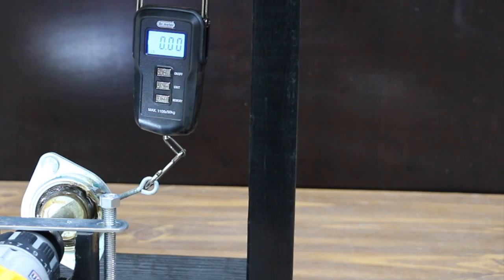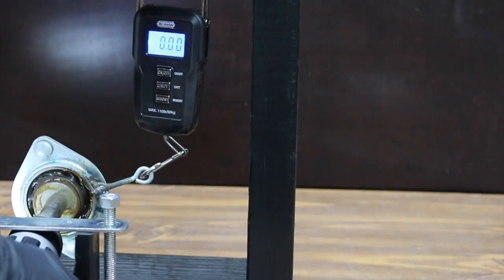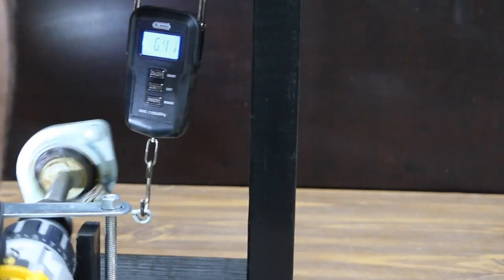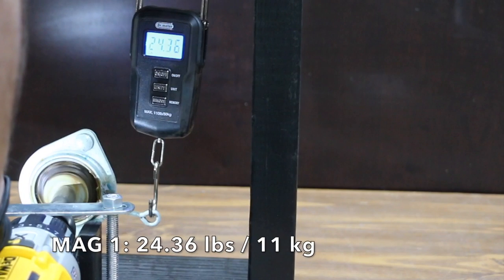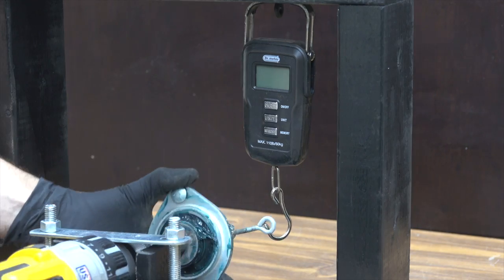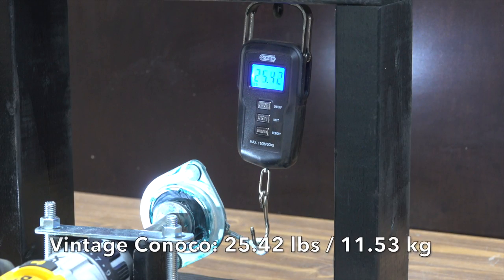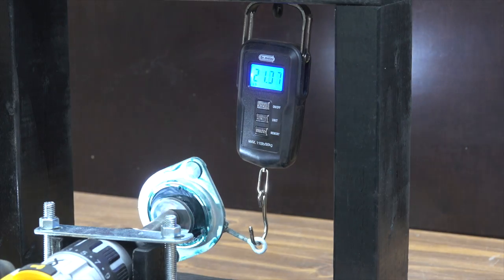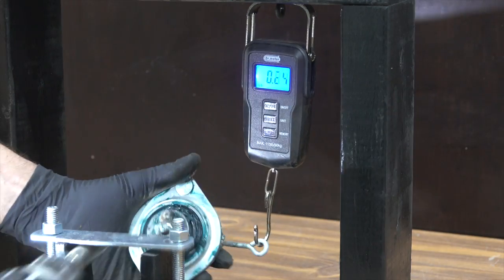It's been right at 24 hours since the bearing was placed in the freezer. Let's first test the Mag 1 grease and we'll measure the resistance to motion in pounds. It took a little over 24.36 pounds to rotate the bearing packed with Mag 1, which is actually sort of high. So it's possible that the vintage grease could win this event. And the vintage grease nearly won at a little over 25 pounds, but it's Mag 1 for the win.